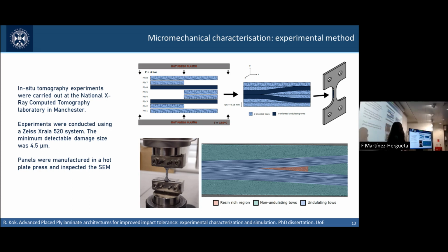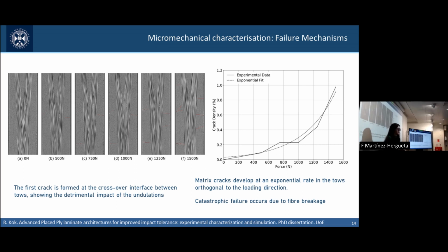This micromechanical characterization was performed in a tomograph in Manchester through a grant obtained by Fibre. And these are more or less the results that we obtained. We measured the crack density for different loads, at different steps, until final failure, which was between 1500 and 1600 Newton. It's going to be a little bit difficult to see. Maybe the main failure mode that we characterized for these loads is matrix cracking. All these cracks appear perpendicular to the loading direction, and they increase exponentially with load.